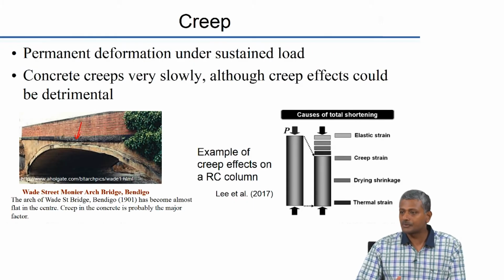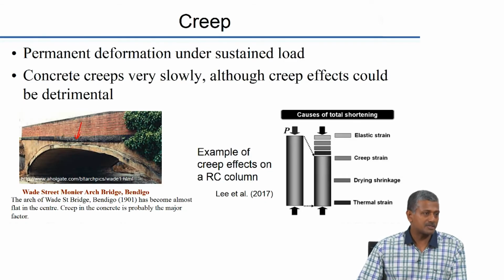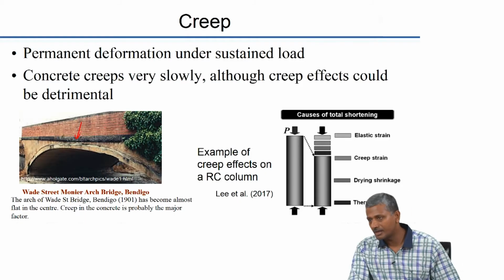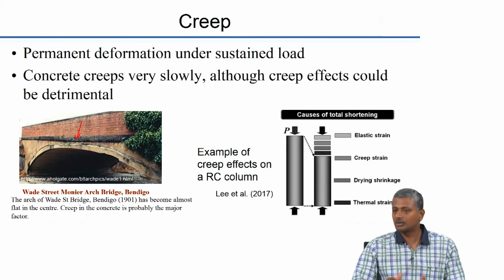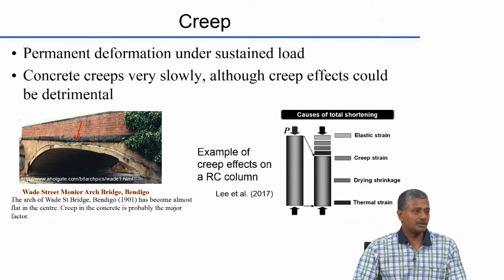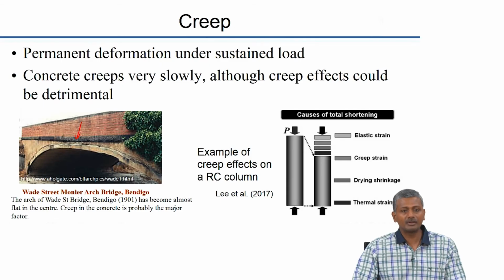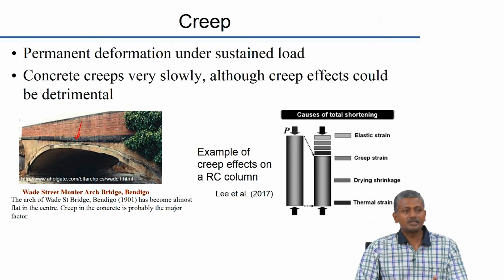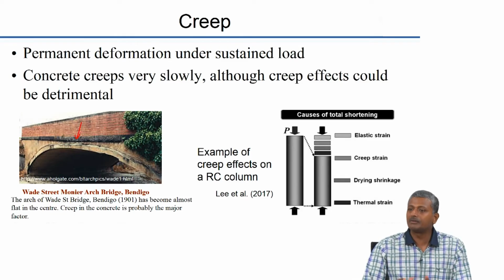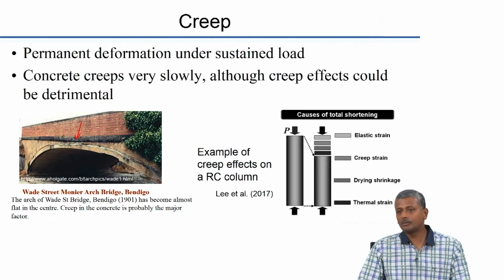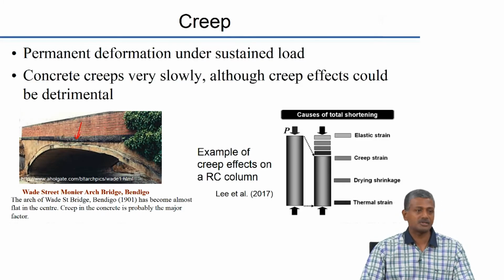Cement concrete, on the other hand, is not as viscoelastic as a polymer, but still the effect of creep can be substantial in cement concrete because we are talking about deformations over a very long period of time. In a polymer, we talk about very short term deformations, which are highly sensitive to the temperature, because asphalt is a material that has a very high viscosity at room temperature, but if you increase the temperature to 60 degrees Celsius, that viscosity reduces nearly 1000 times, or no, more than that, 10,000 times. So, such drastic changes in viscosity can happen in that material, but not in concrete. Concrete is not going to be so highly viscous, but still it is much higher than that of a metal. Metal, in response to regular working temperatures, will not creep as much as concrete, and concrete does not creep even a fraction of polymers, but then still the resultant stresses could be substantial.